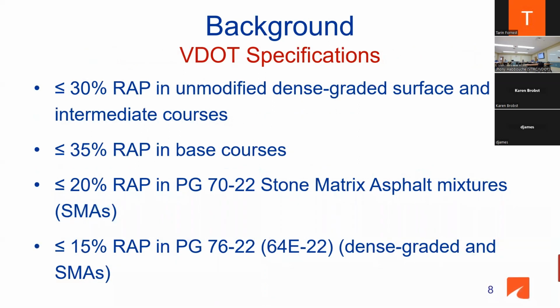So VDOT spec, as of today, allows up to 30% RAP in unmodified dense graded surface mixes. So the surface mixes will have 30% RAP. In base course, that goes up to 35% RAP. In stone matrix asphalt mixture, or the gap graded mixture, they allow up to 20%. That's with the PG70-22. And then when we go into interstates, when we start using polymer modified, we still limit this to 15% just to have better control on the stiffness. And we do not want to dilute the amount of polymer being used in the asphalt binder.